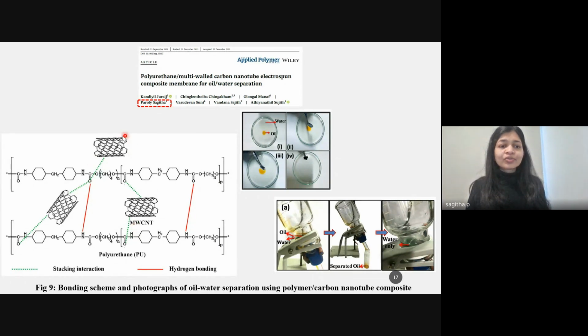For that, we have used multi-walled carbon nanotubes as the filler material in the polymer. So when we added the multi-walled carbon nanotube into the polyurethane matrix, it enhanced the hydrophobicity and developed a super hydrophobic surface. So we could obtain a super hydrophobic membrane using the functionalization with multi-walled carbon nanotube. And when we tried the oil adsorption property of this membrane, what we found is that this membrane could selectively remove oil particles from the oil-water mixture.